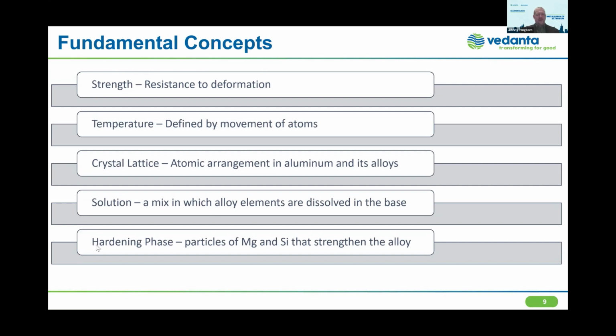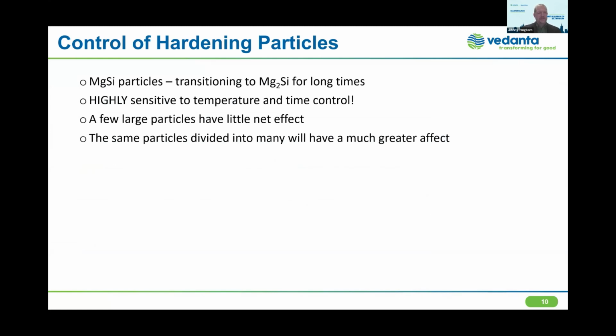We'll contrast that a little bit with hardening phases, which are actually distinct particles that come out of solution. And in our case, again, magnesium and silicon particles, and we control those in a way that strengthens the alloy. So hardening particles, these are magnesium and silicon particles at longer times and temperatures. As the particles grow, they will become Mg2Si, but there are many other phases in the spectrum. This is, again, highly sensitive to temperature and time control. Again, remember, the definition of temperature is how active the atoms are moving.